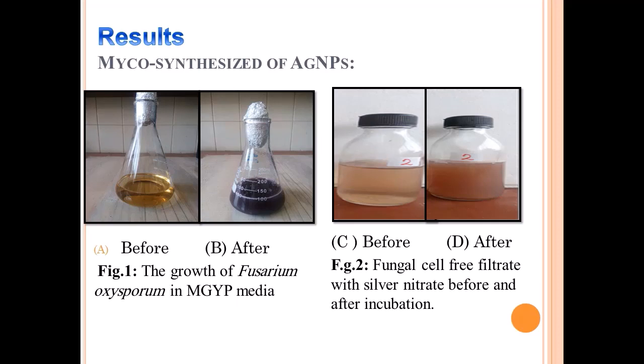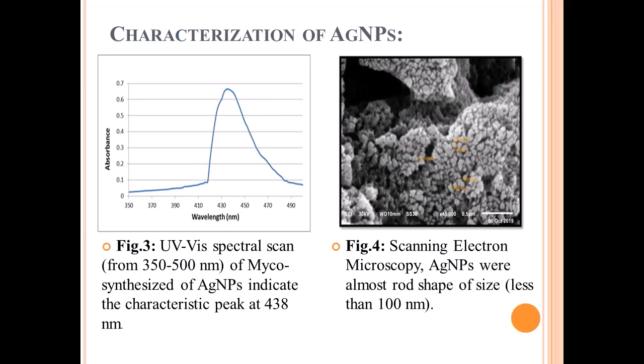Figure 1. The growth of Fusarium oxysporum in MGYP media, A before, B after. Figure 2. Fungal cell-free filtrate with silver nitrate before and after incubation, shown in picture C before and picture D after. Characterization of silver nanoparticles. Figure 3. UV spectral scan from 350 to 500 nanometers of myco-synthesized silver nanoparticles indicates a characteristic peak at 438 nanometers.